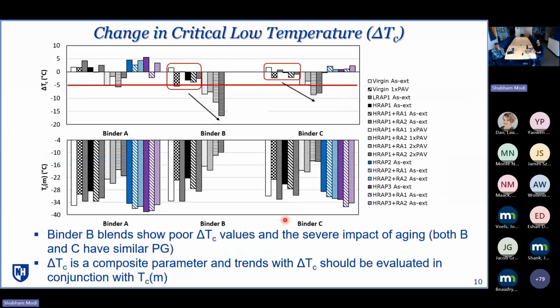To discuss the delta TC parameter, what we observed is that the aging susceptibility of binder B was also observed here. We can see that inclusion of recycling agents sometimes negatively impacted delta TC, meaning that it moved to the more negative side. So we went further and evaluated the component parameter TCM as well. Here we can see that the inclusion of recycling agent improves the TCM parameter. However, as delta TC is a composite parameter, the relative changes of TCM and TCS result in the delta TC showing the negative impact. Therefore, delta TC should be evaluated in conjunction with TCM as well.